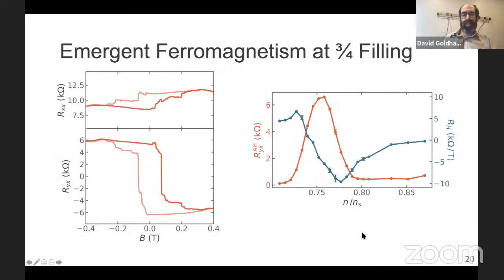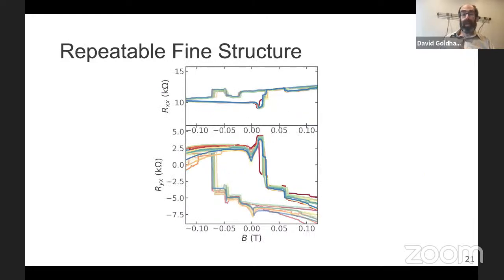So this magnetic signal is very tightly present at 3/4 filling, meaning 3 electrons per moire cell, or 1 hole per moire cell. So there's, I guess, 1 moment per moire cell, and these moments are aligning. There is a magnetic signal even out to much higher filling, but it becomes quite small. And also at 3/4 filling, we go from signatures of having electron-like carriers to hole-like carriers. So it seems like there's a gap or a semi-metal at that point.